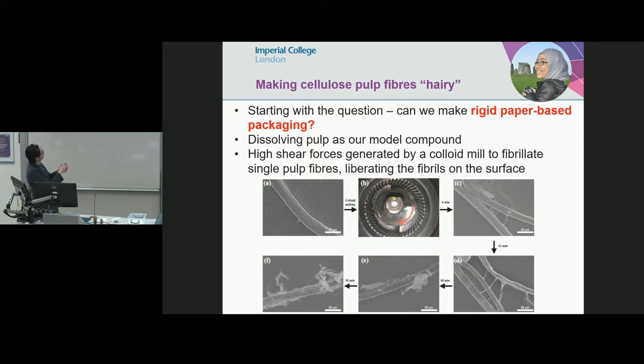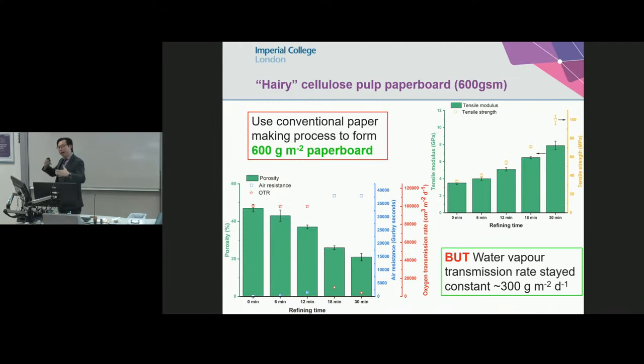Essentially, here's your single pulp fiber. You put it through a grinder. Like I said earlier, every single grinding process shears the surface fibers apart. And the longer you grind, the smaller it becomes. If you do it just right, you can retain that original starting fiber and only the surface of the fibers gets fibrillated. So that's what we call hairy pulp fibers. When you pack these hairy pulp fibers together, something magical happens.